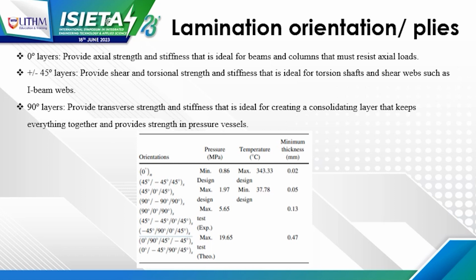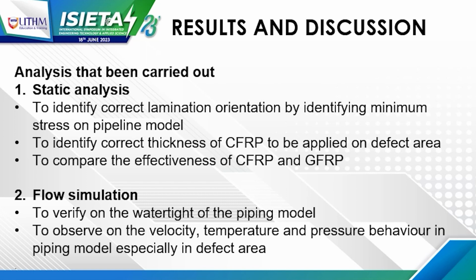with different lamination orientations. There are two analyses that will be carried out in this research. The first is static analysis, to identify the correct lamination orientation for a 90 degree defected elbow at the extrados location, to identify the correct thickness of carbon fiber to apply on the defect area, and to compare the effectiveness of carbon fiber and also glass fiber. And the second analysis is flow simulation, to verify whether it is watertight, and to observe the velocity, temperature, and pressure behavior in the piping model, especially at the defected area.